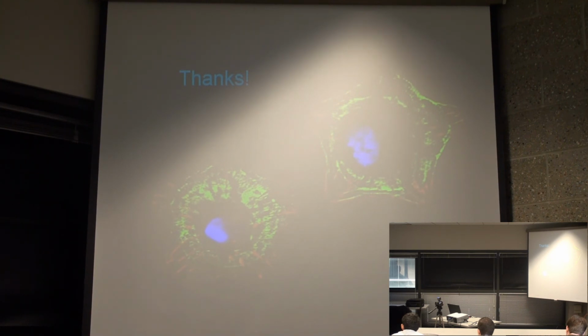Sure. We're pretty new at being able to do it robustly, but absolutely, there are new hydrogel chemistries coming out all the time. Kristi Anseth is one of the names that pops in, where she can use two-photon techniques to locally polymerize gels in a three-dimensional way that maybe mimics tissue shape better than a 2D material. And there's a lot of control over some of these PEG-based multi-arm gels, where you may be able to change the length of the PEGs and rationally incorporate peptide ligands into these scaffolds. So with synthetic scaffolds, I think we're starting to develop cool tools. I think we're a long way off before we can translate those into something biologically relevant, but maybe not too far. That's my feeling of the state.